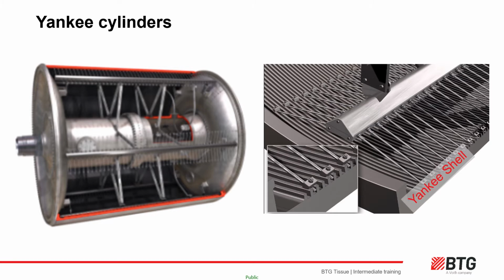Cast iron is a relatively soft and porous material, so the surface can wear quickly, requiring it to be ground periodically, especially if the wear is uneven. After each grind, the shell thickness is reduced. Eventually, the thickness reduction reaches a critical point called the derate point. This means the working pressure of the Yankee and/or the linear load of the press must be reduced to run the Yankee safely. This reduces machine capacity.